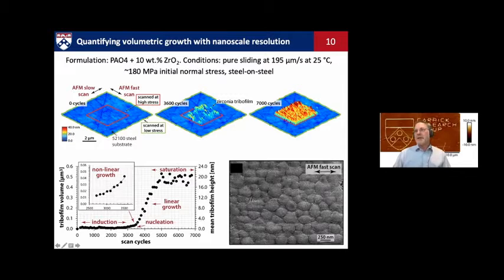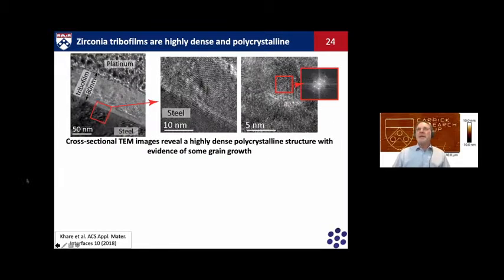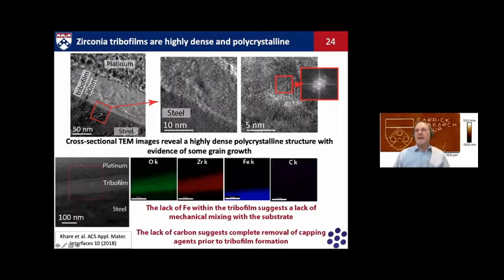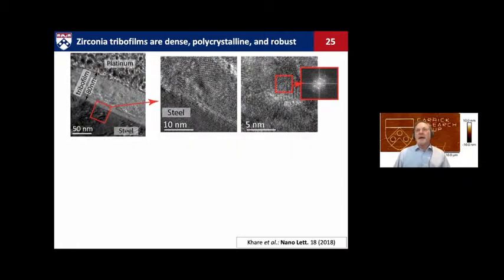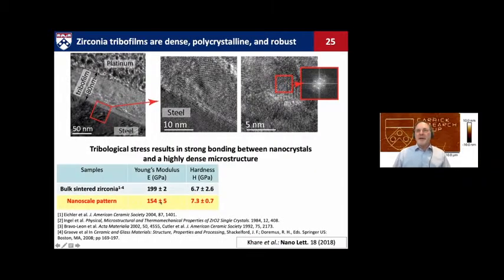And this is a top view in scanning electron microscopy. Interestingly, not that different than ZDDP, there is also a sort of pad-like structure, this bumpiness to the film. We can investigate the cross-sections of this film in the TEM, and again, we see a dense polycrystalline nature, a well-fused film. We verify with energy dispersive spectroscopy that it is largely composed of zirconium and oxygen. We see very little iron mixed in, and the carbon from the capping agent is removed. We see that the modulus and hardness of the film is close to that of bulk zirconia.